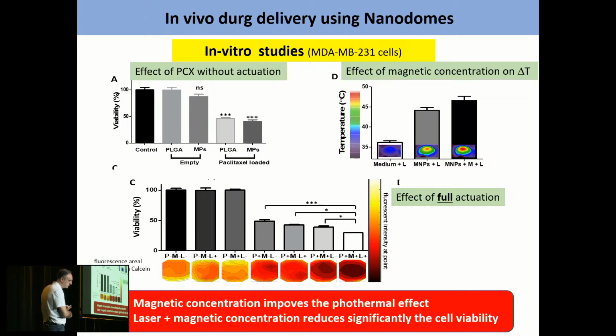And here, using fluorescence, we can see the distribution of the effect in the cells, where they die, so to say. And you can see that when we don't have the laser on, the effect is quite homogeneous everywhere. But when we do the magnetic concentration with the laser, the effect is concentrated where we have the laser, meaning that we've managed to concentrate the particles in a certain area, and then they increase the effect in that area.